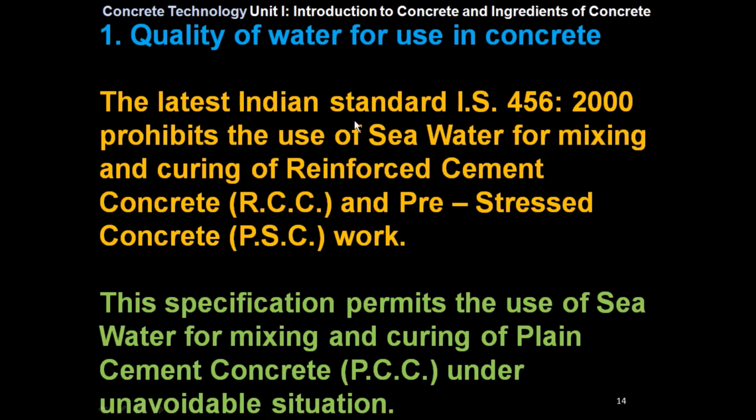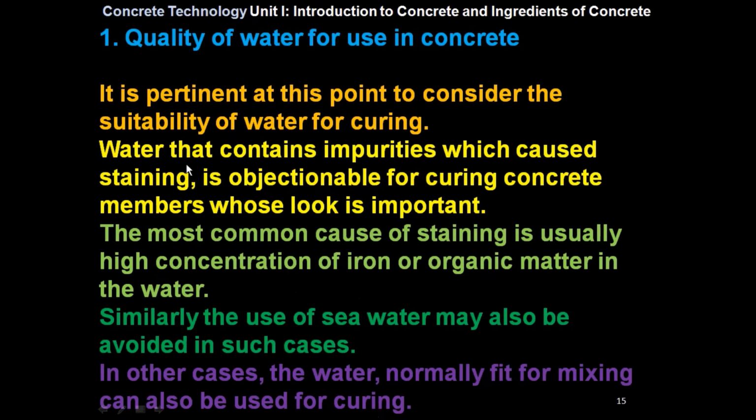The latest Indian Standard, that is IS 456:2000, prohibits the use of seawater for mixing and curing the reinforced cement concrete, that is RCC, and prestressed concrete, that is PSC work. This specification permits the use of seawater for mixing and curing of plain cement concrete, that is PCC, under unavoidable situations. It is pertinent at this point to consider the suitability of water for curing.